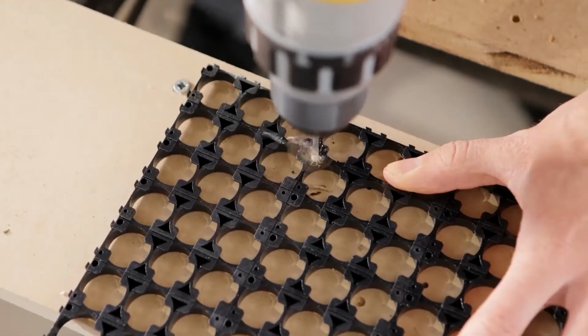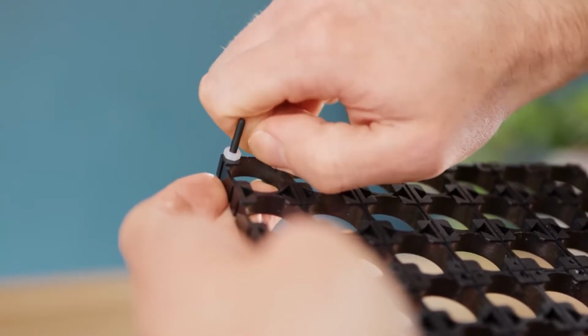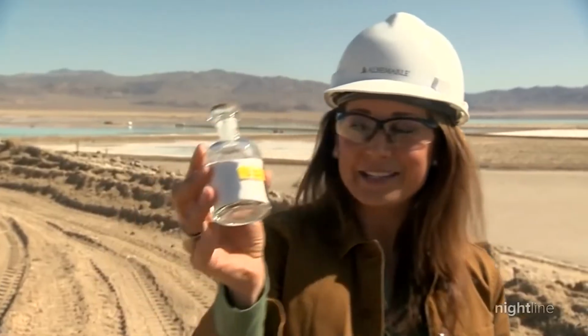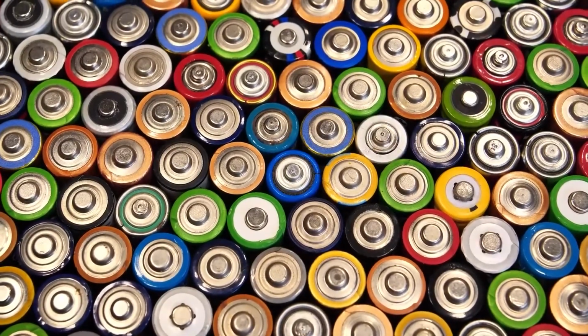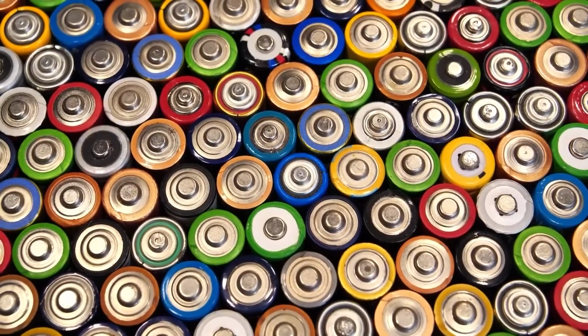The LieNA technology, which is patented by Lithium Australia, involves initial treatment of the waste spodumene to form synthetic lithium sodalite, which can be easily recovered. Lithium is then easily extracted and purified in relatively straightforward processing steps, and finally isolated as lithium phosphate, which can be directly used in the manufacture of lithium ferrophosphate batteries.